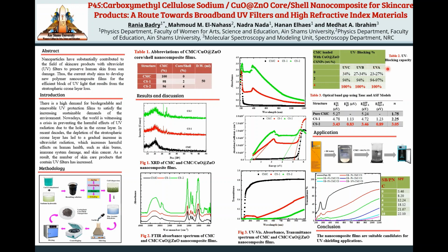This table presents the UV blocking percentage of pure CMC and CMC with different concentrations of core shell nanoparticles in the 3 regions of the UV radiation. And we found that the film containing 4 weight percentage of core shell nanoparticles can block 100% of the incident UV radiation, which is a very good result.